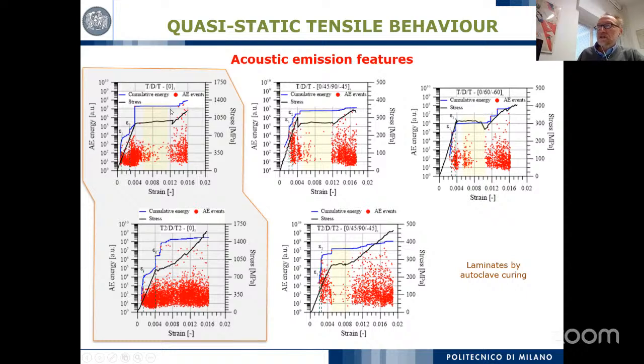And this progressive delamination, as I mentioned, is completely different when changing the sublaminate, where in the case of the second set of sublaminates, this is very noisy because it's much faster. You have different positions where the delamination starts, and so you have quite completely different pseudo-ductility behavior, if this can be named pseudo-ductility.